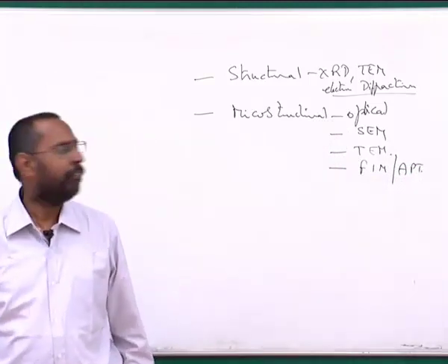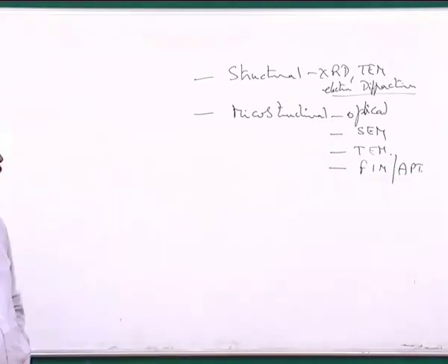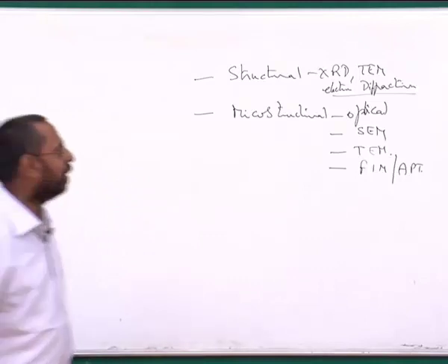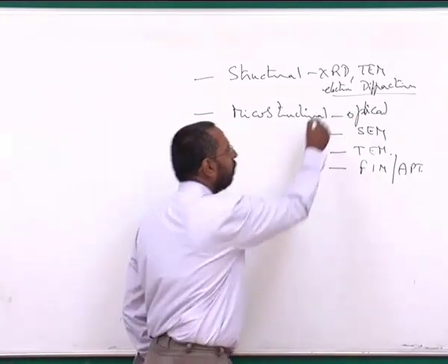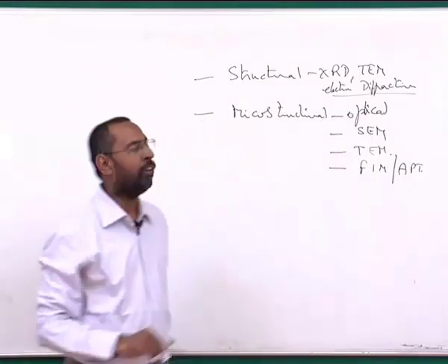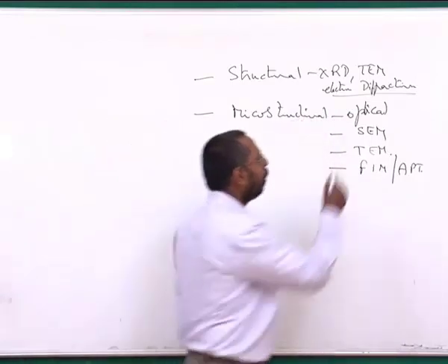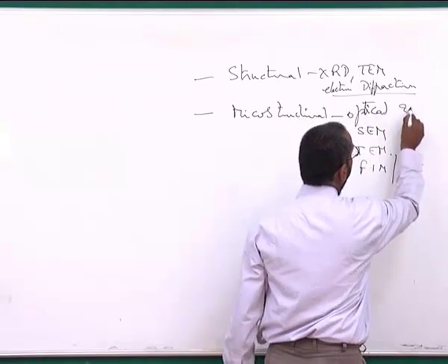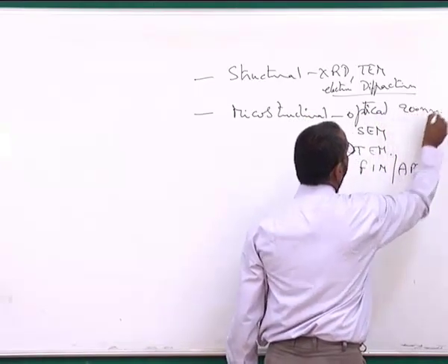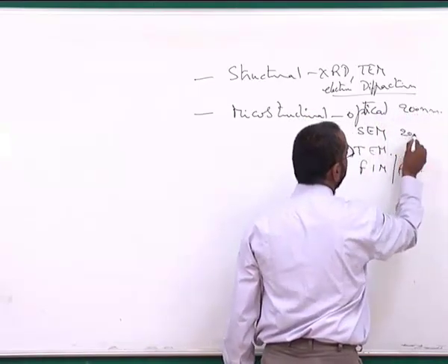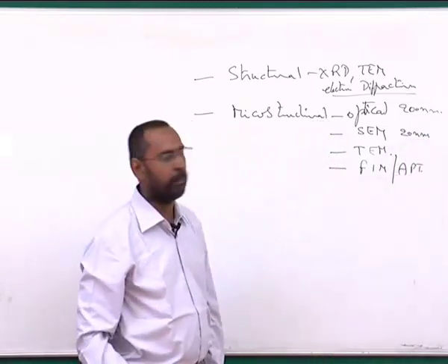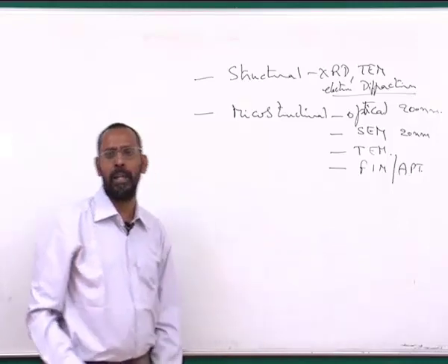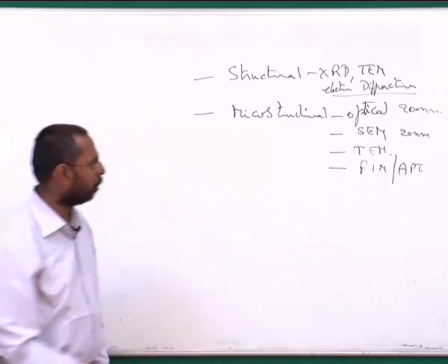So we looked at various levels of microstructural information, where as you go down you would have seen that the resolution keeps on increasing. So we have a low resolution of the order of around 200 nanometers or so here, and here you may be ending up with let's say about 20 nanometers with a normal SEM, and maybe with a FEG SEM you may be ending up with about 5 nanometers or so.